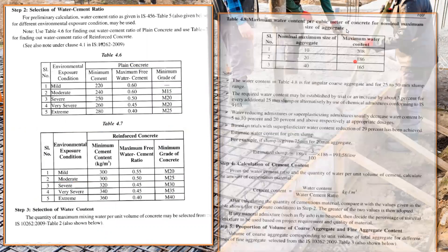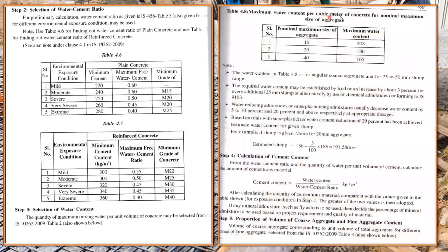Step three is the selection of water content. The maximum water content per cubic meter of concrete for a nominal maximum aggregate size of 20 mm — which is standard for normal RCC structures — is 186 kg. Whatever water-cement ratio we select, the resulting water content should be kept below 186 kg as far as possible.